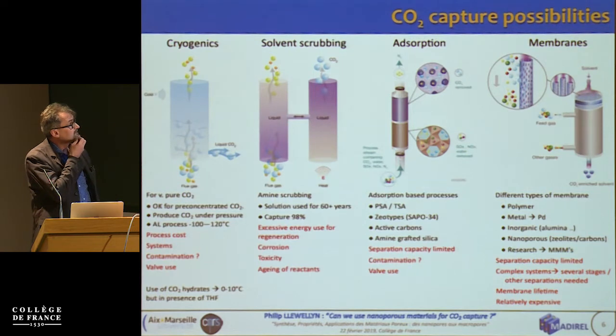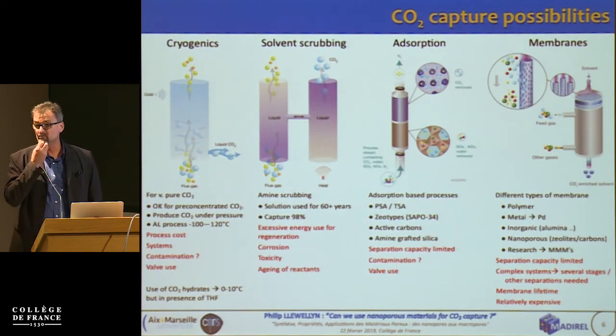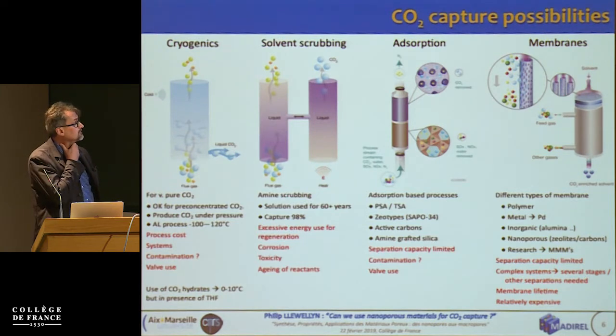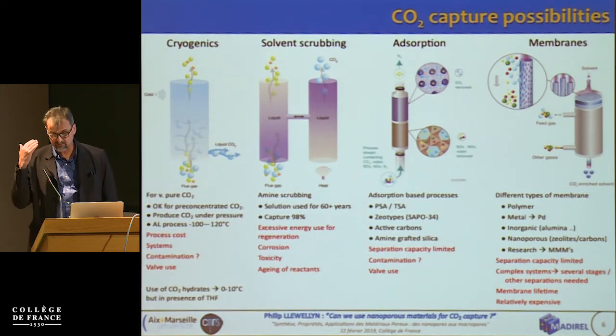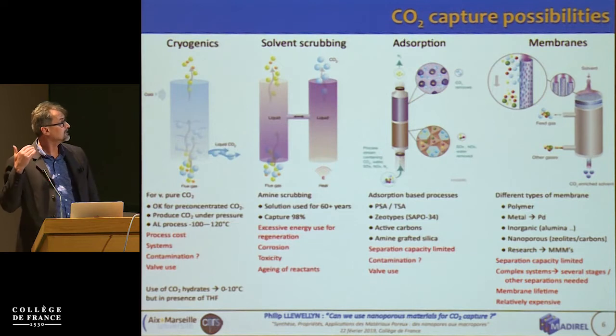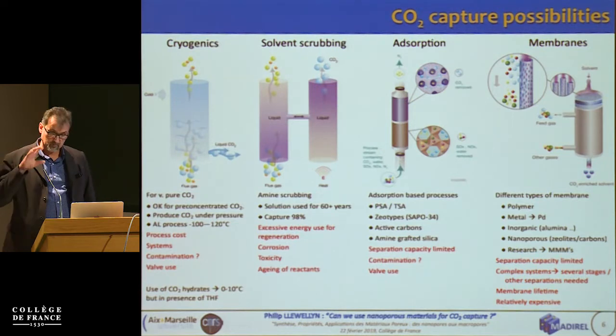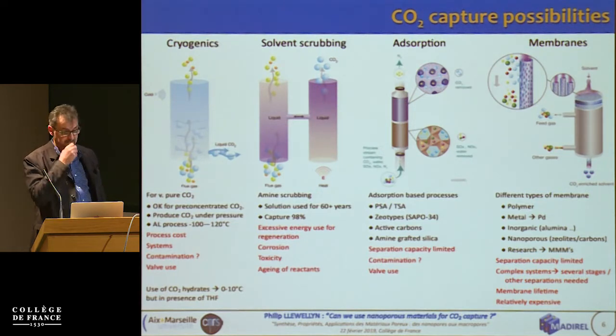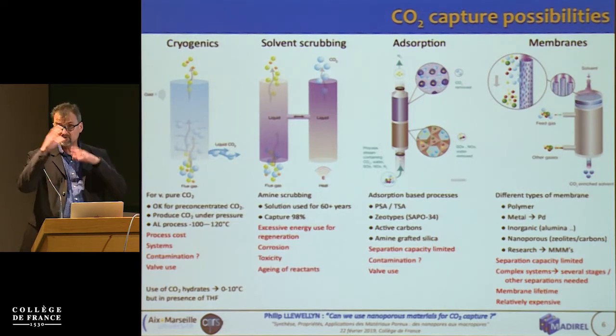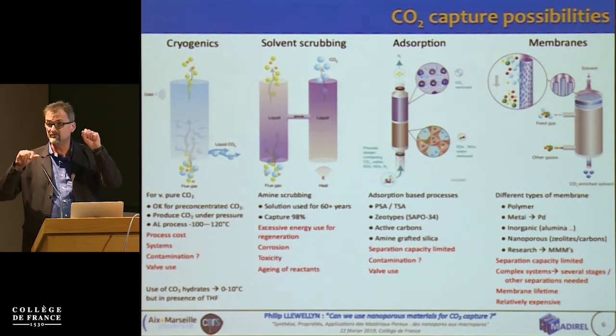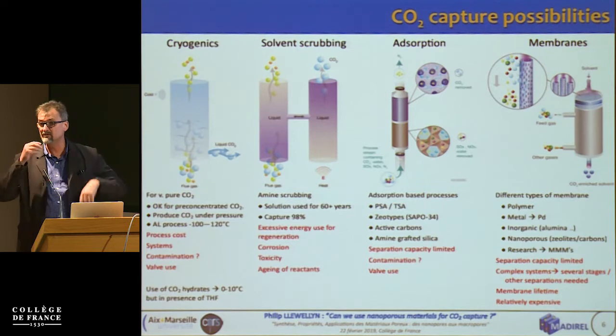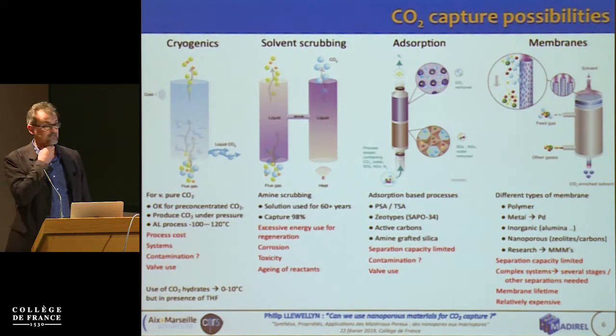The Air Liquide process is at below minus 100 degrees Celsius, so it's really, really low temperature, which gives us all the problems of process costs, the system itself, and of course real problems if there's any sort of contamination. And also we have a process with these sort of things. We've got to use valves. So opening and closing a valve at minus 100 degrees C is not that easy.